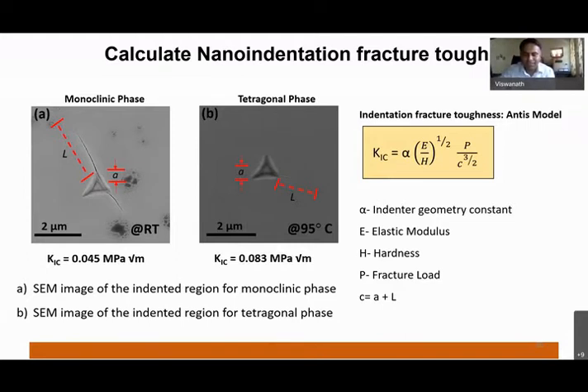But there is one surprising thing, which is the reason I'm presenting here. Of course, there is nothing new in measuring fracture toughness. We measured these values almost 2 years back. The student graduated and went abroad for a postdoc. I was not confident in publishing the paper, and of course, we have not published even today. The values are very, very low compared to what you would expect for any ceramic material. It's like 0.045 and 0.083.